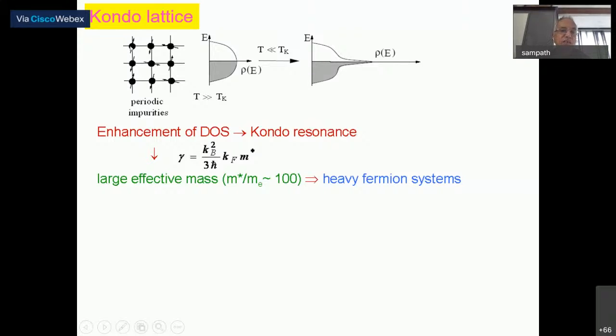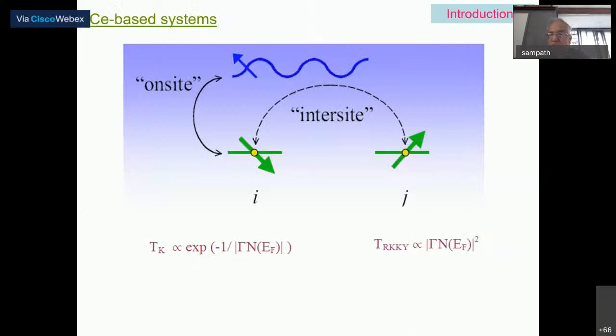Because of this on-site interaction, which is essentially due to some degree of 4f delocalization, you have an enhanced density of states at the Fermi level, there is a renormalization of the density of states, the heat capacity goes up, the linear term at low temperature goes up. Therefore, they are called heavy fermions. Okay. If you take a concentrated system like, for example, cerium metal or cerium aluminium 2 compound, you have two interactions. One is the on-site interaction, which is the Kondo effect, going exponentially with the exchange interaction, and the other is the intersite interaction, which promotes magnetic ordering. One is killing magnetic ordering, the other is promoting magnetic ordering, which goes like the square of the function. Then these two will compete depending upon the strength of each interaction. One can dominate over the other.